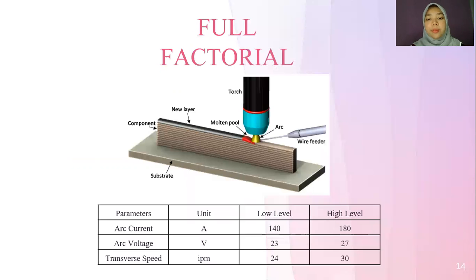In a full factorial experiment, responses are measured at all combinations of experiment factor levels. As in my project, the full factorial optimization of 5 samples of experiment, arc voltage, arc current, and welding speed have been chosen as input parameters, and weld width of deposition is selected as output parameter.